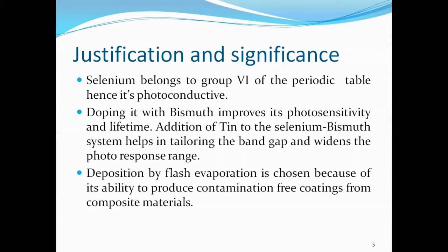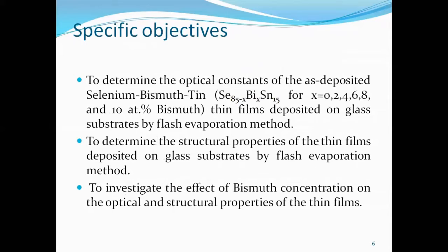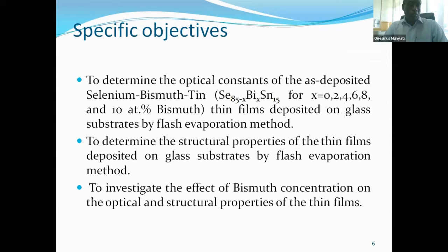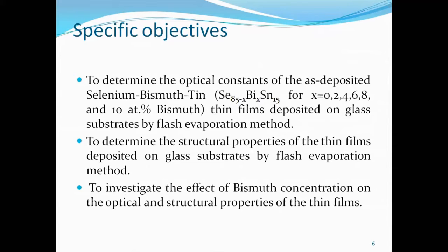We chose the flash evaporation method because of its ability to produce contamination-free coatings from composite materials, because it is done under vacuum. Now, our main objective was to determine the optical properties of the selenium, bismuth, tin films, and these are the specific objectives: to determine the optical constants of the selenium, bismuth, tin films. I've tried to include the percentages at this initial stage so that you can follow my discussion later.